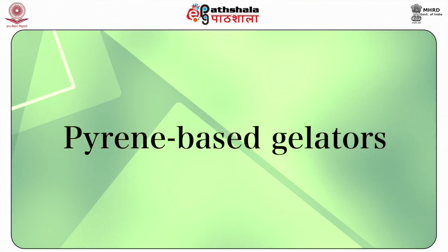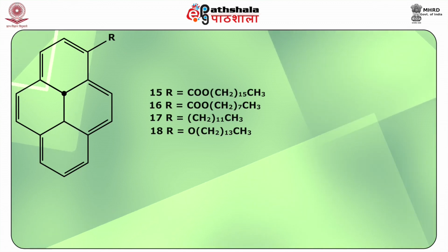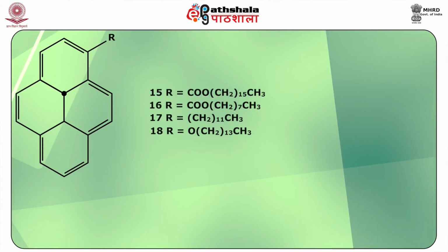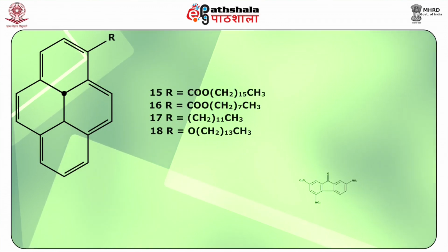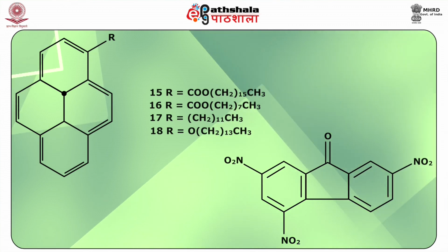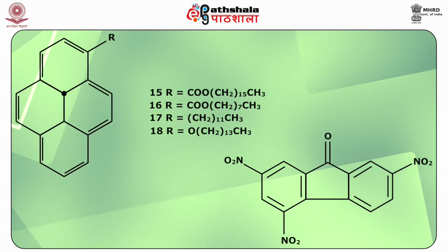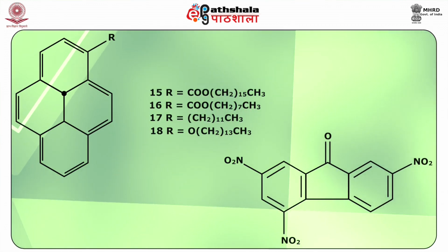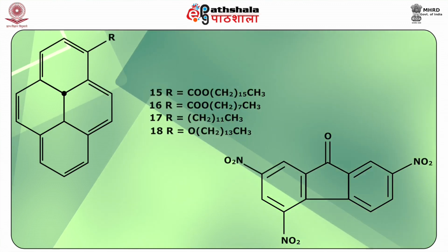Firstly, pyrene-based gelators. The pyrene derivative compounds 15 to 18 formed gels with different organic solvents in the presence of trinitrofluorenone, TNF, due to charge transfer interaction between the pyrene unit and TNF. The gels so formed have been found to be stable at room temperature for several days.